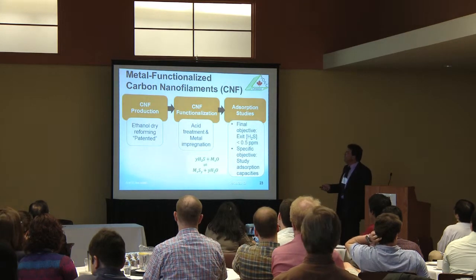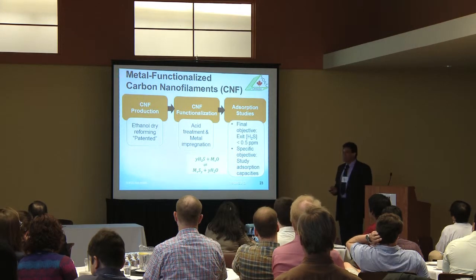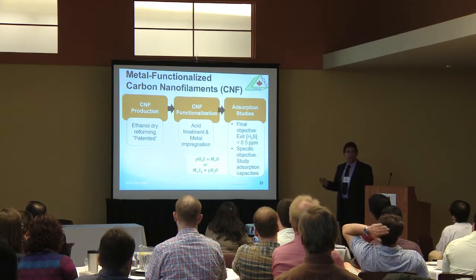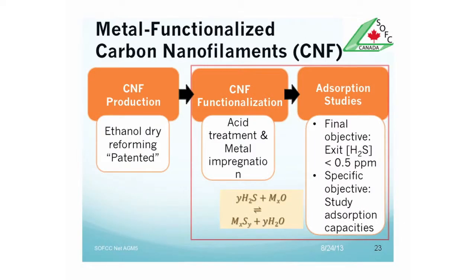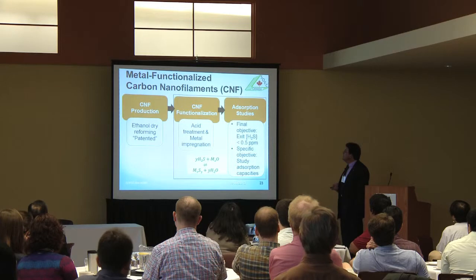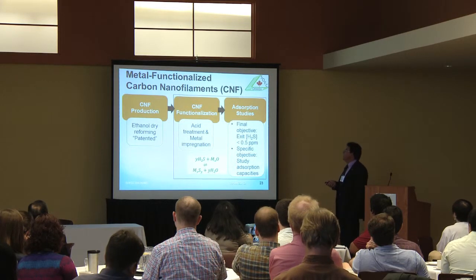So how do we do that? Production of carbon nanofilaments in-house, also using a patented process through ethanol dry reforming. Then the carbon nanofilaments are functionalized by acid treatment to introduce oxygen anchors and then make metal impregnation. And finally, the adsorption studies. So essentially, this is the PhD thesis topic of Clémence.